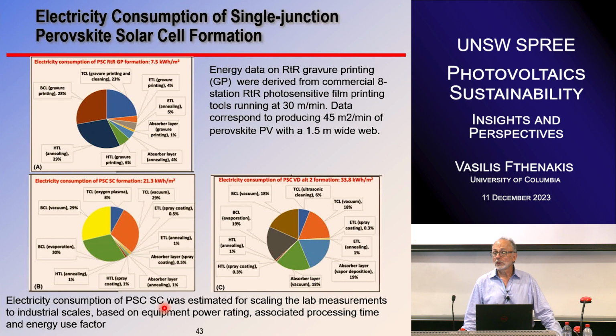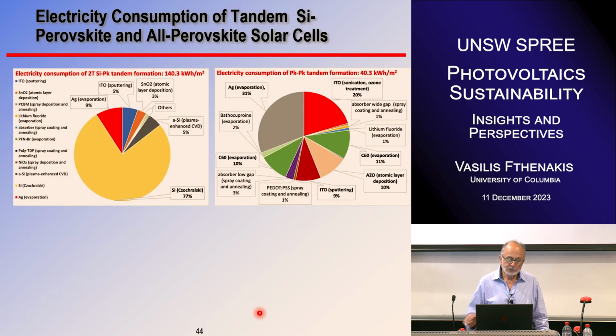Having data on equipment and the times it takes in processing, so they are not real commercial data. These are commercial data here. So maybe the situation with spray coating can become better, we don't know. Also, what we see here though is that in tandem, the biggest energy use is on the silicon that is underneath, not on the perovskite. So that's the biggest one.